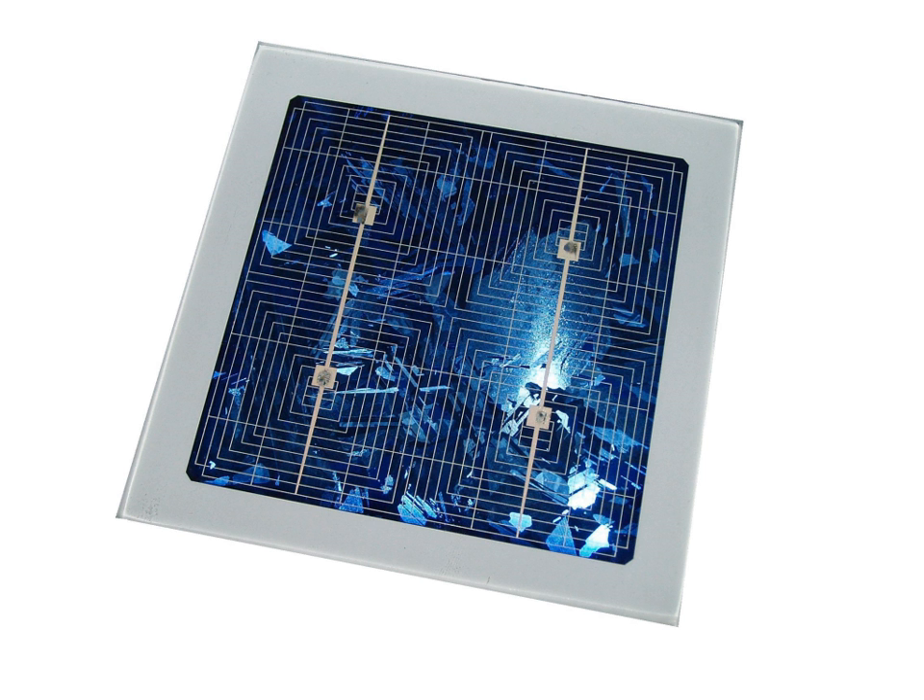This transparent, UV-absorbing system was achieved by using an organic-inorganic heterostructure made of the p-type semiconducting polymer PEDOT:PSS film deposited on a niobium-doped strontium titanate substrate. PEDOT:PSS is easily fabricated into thin films due to its stability in air and its solubility in water. These solar cells are only activated in the UV region and result in a relatively high quantum yield of 16% electron-to-photon conversion.